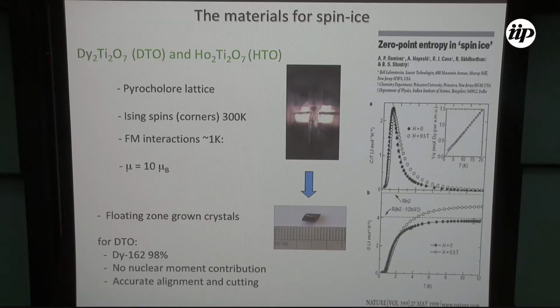So one way in which people showed that this hand-waving way of counting entropy worked reasonably well for the system was by doing exactly the same thing that people had done for water ice, which is measuring the specific heat, integrating the specific heat, and seeing whether that matches with your expectations or not. So this is a work by Ramirez and collaborators in 1999. And you see, this is what you get for the specific heat. Let's first focus on the zero field. There you have this peak close to 1 Kelvin.